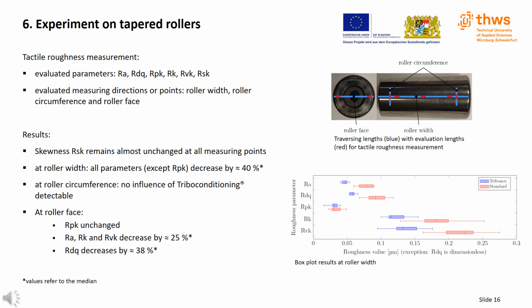Surprisingly, the skewness RSK remains almost unchanged at all measuring points. At the roller width, all examined parameters, except for the reduced peak height RPK, decrease by about 40%. The values each refer to the median. The diagram on the bottom right shows the corresponding box plot results at the roller width. The significant improvement due to triboconditioning is clearly visible.